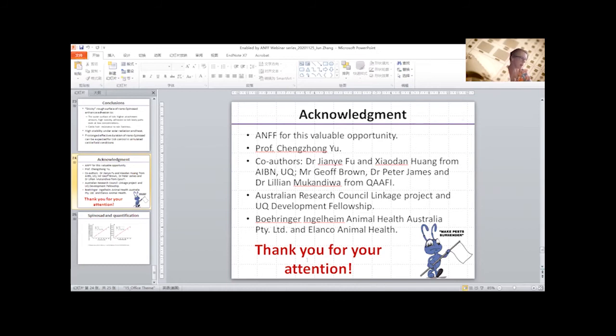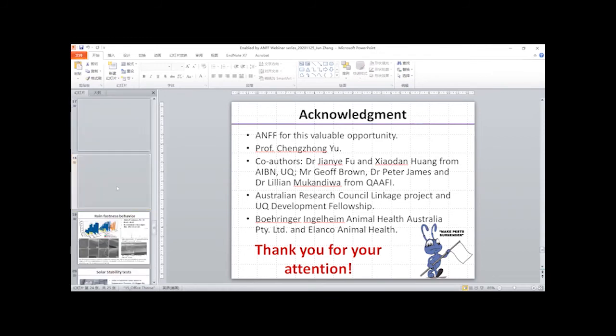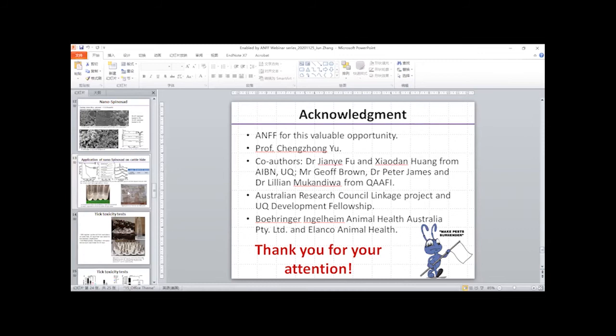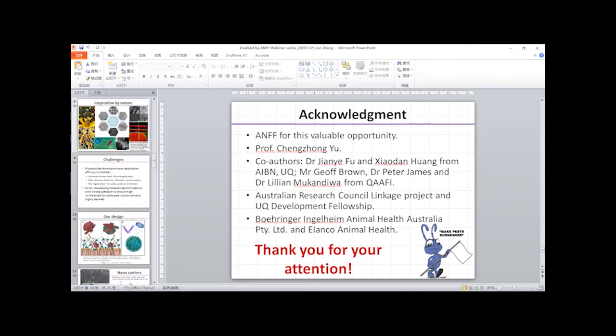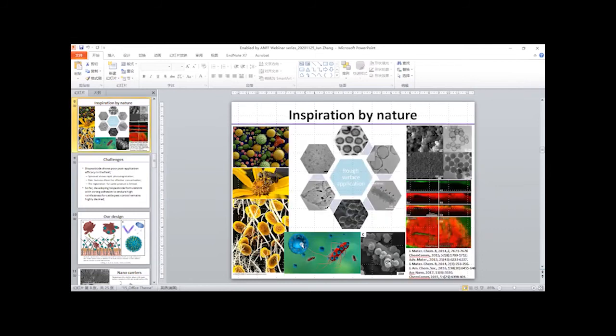We have time for one, and I will kick off with this one. So you were talking about your rough silica particles. How do you actually create that roughness? This is a method we developed before. We use a co-condensation method. First, we use a Stöber method to create a silica spherical sphere, which will become the hollow cavity in the future.